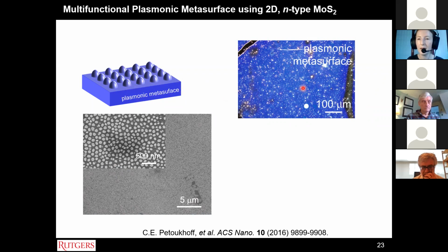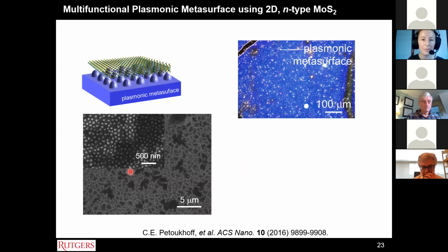This is the dark field scattering from that surface. You can see the blue scattering, which is characteristic of the silver particles. And this is just the scanning electron microscopy of the bare surface. And then he applied a MoS2 layer by transferring a chemically exfoliated layer onto the plasmonic surface.